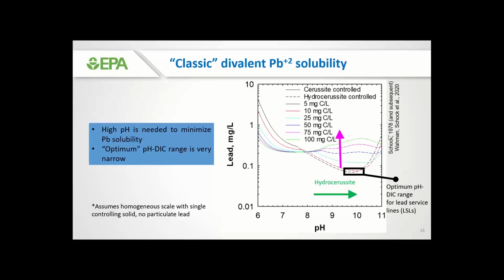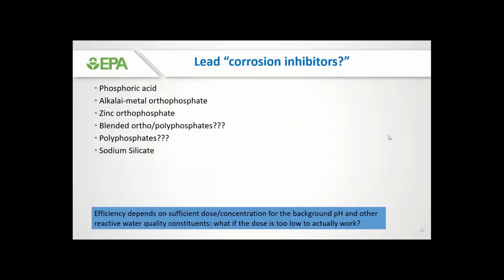So the truly optimum range of pH and DIC are very limited, very narrow. There's certainly systems that can accomplish that, but not every system will be able to do that, which then brings us to corrosion inhibitors, chemicals that we add into the water to help control lead release. There's a lot of different kinds. Orthophosphate can be added either alone or as a zinc orthophosphate. You probably have heard of polyphosphates as well, added either alone or as blends with orthophosphate.